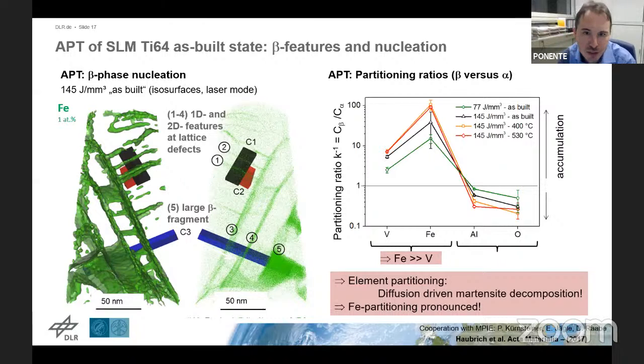And this way, we were able to learn a bit about the beta phase formation using the combination of techniques. And we were surprised to find that the partitioning is actually most pronounced not for the main beta stabilizer vanadium, but it's most pronounced for the iron in this case, much more sensitive than the vanadium, which also allows us to better track all these precursors in the material, for instance.